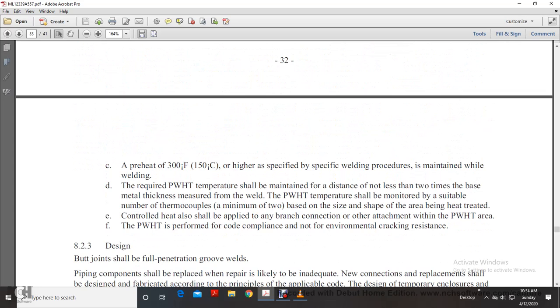Preheating of 300 degrees Fahrenheit or higher, as specified in specific welding procedures, is maintained while welding. Post-weld heat treatment is required. The temperature should be maintained for a distance not less than 2 times the base metal thickness, measured from the weld. Post-weld heat temperature should be monitored with a suitable number of thermocouples, a minimum of two, based on the size and shape of the piece being heat treated. Controlled heat should be applied with consideration for branch connections and other attachments within the post-weld heat treatment area.